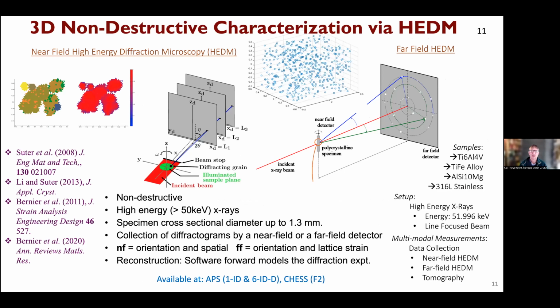Okay, so let me walk you extremely quickly through what is high energy diffraction microscopy. The basic idea is remarkably straightforward. You mount your sample on a rotation stage in front of a monochromatic high energy beam, for example, at 1-ID at the APS, and you take a diffraction pattern. But more than that, what you want to do is take a diffraction pattern at more than one sample detector distance. So that's that diagram there.